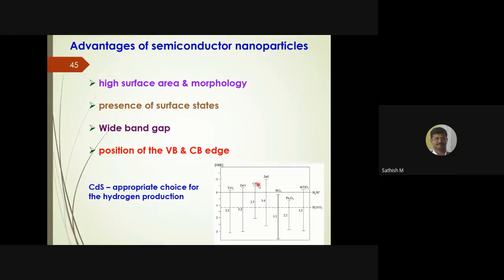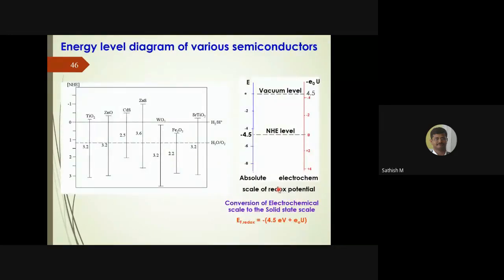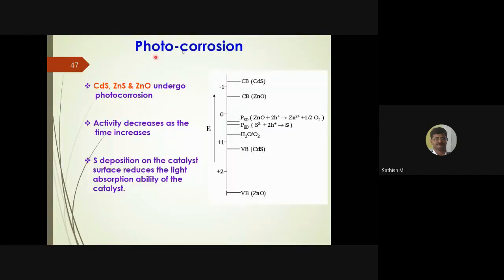But one of the promising catalysts is cadmium sulfide, but unfortunately cadmium sulfide is very corrosive in nature. I'll just explain what is very corrosive. And again, those who are new to this field, maybe you can use this kind of equation to correlate your conventional electrochemical scale into the absolute electrochemical scale, so that you can theoretically calculate the valence band level or conduction band level of your semiconductor against the conventional reduction and oxidation potential of the particular pollutant or reduction reaction, so that you can work out whether this catalyst could be used for this particular oxidation or reduction reaction or not. So here I just explained what photocorrosion is.